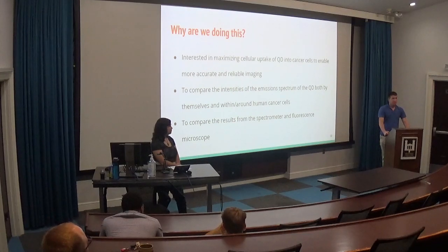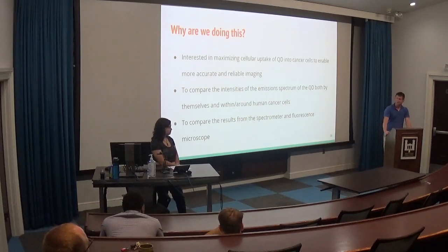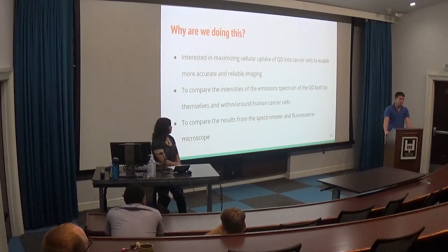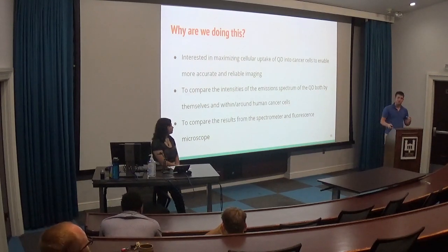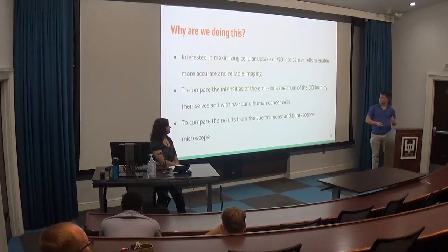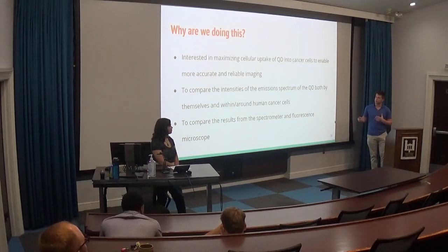In the first semester, we were primarily interested in maximizing the cellular uptake of the quantum dots within the A549 cancer cells. To do this, we analyzed cell viability data from a number of different samples, all injected with different concentrations of quantum dots, and pretty much found the concentration that is going to lead to a lot of cellular uptake without compromising the viability of the cells that we want to keep.